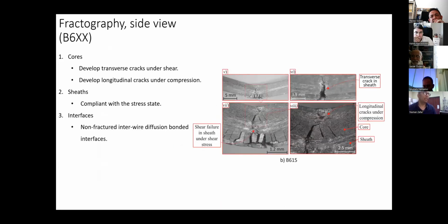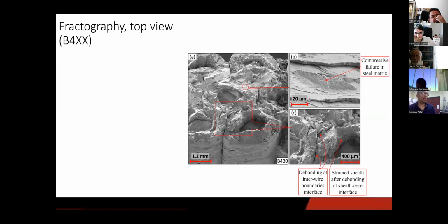That can only be seen if we go for the transverse analysis. Transverse analysis of the wires is shown here. What we saw there is something which we saw here also. Sheath core interfaces are most vulnerable to the bending stresses. Interwire interfaces are most vulnerable to the bending stresses, and they fail because you see these cracks.